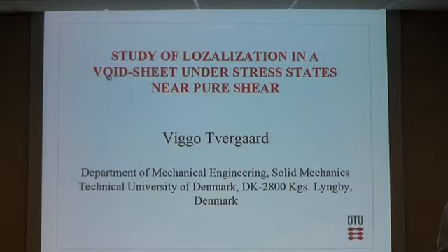It's not so clear here, but these end up being completely horizontal, and that means that in these 3 upper curves, we end up seeing a localization. This void sheet develops into a shear band where failure will happen in a so-called void sheet. But that does not happen here, as you cannot see very clearly, but we'll see on the next slides.